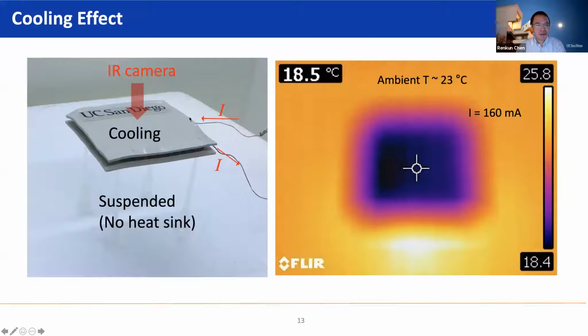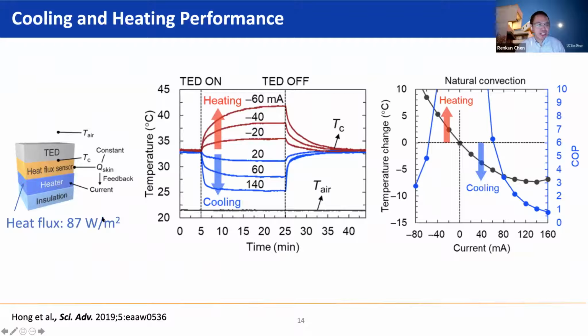So obviously you can see that when you put this device, when there's no heat input, you can see a large cooling effect, in this case from 25 to 18 degrees Celsius, about 7 to 8 degree cooling. And we can also put the device on a heater to simulate the heat flux from skin, about 90 watt per meter square. And depending on the direction of the electrical current you're putting, when you turn on the current, in a few minutes, you can achieve a stable heating or cooling effect. And what is also important is for both the heating effect, which is showing as a positive temperature change here, and the cooling effect, which is showing as a negative temperature change, you have this COP. So this blue curve shows the COP of this device for both heating and cooling. The COP could be greater than 3 for heating and greater than 1 for cooling. Under certain conditions, cooling COP can also be greater than 3.